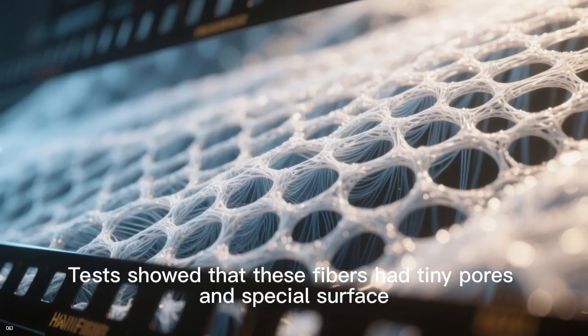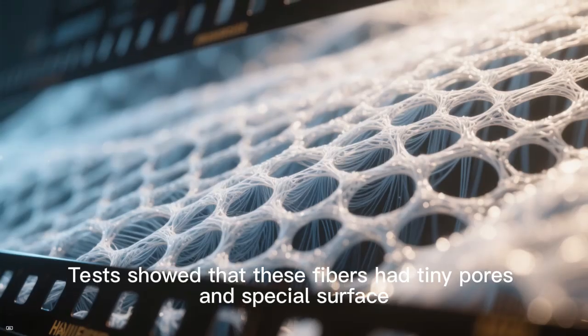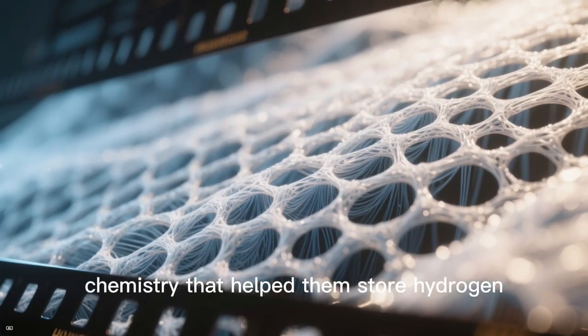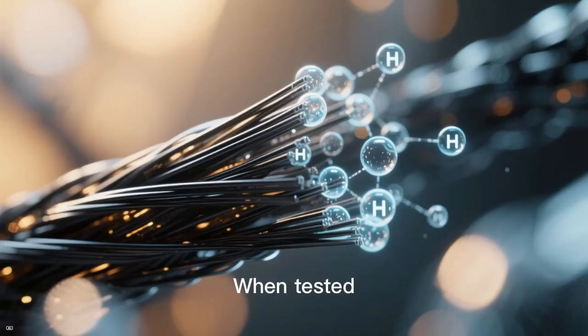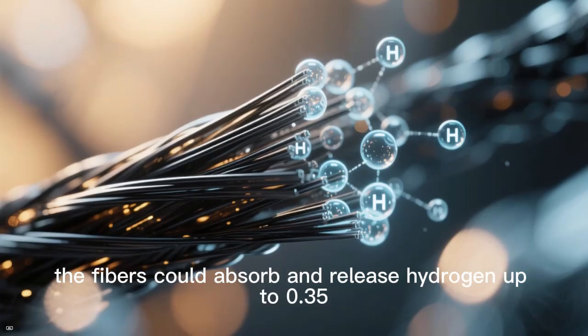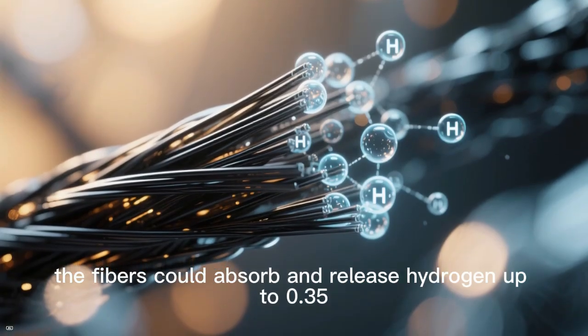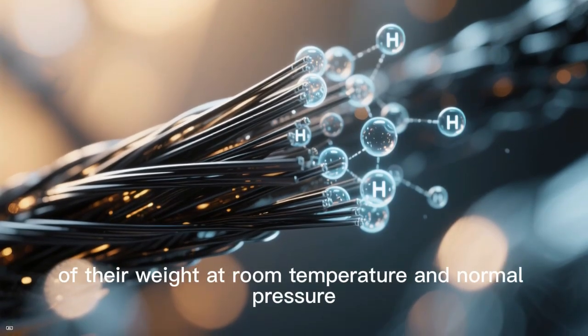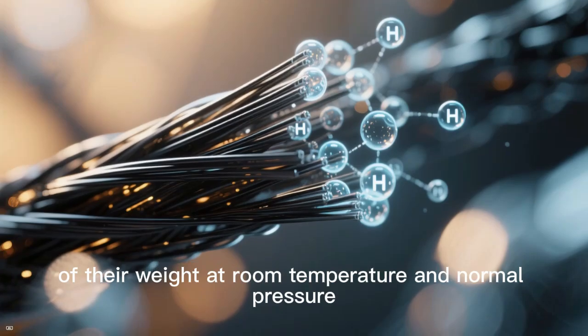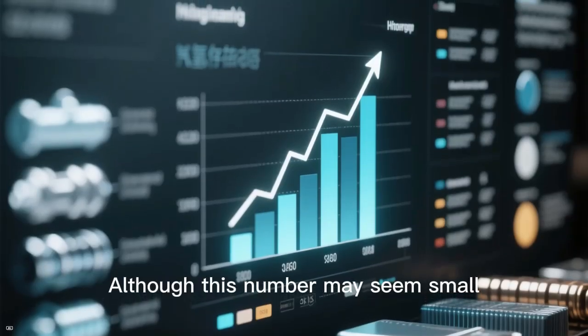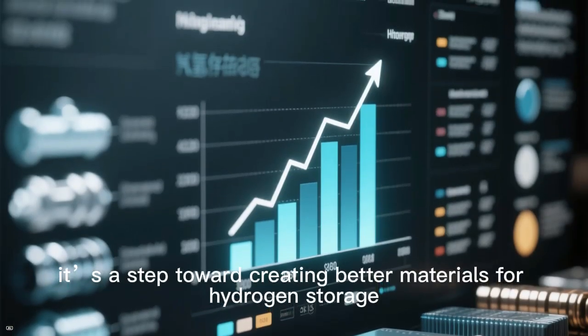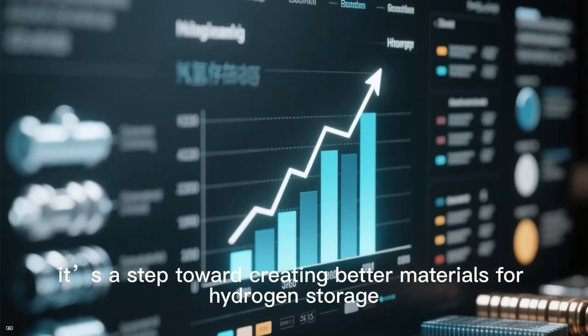Tests showed that these fibers had tiny pores and special surface chemistry that helped them store hydrogen. When tested, the fibers could absorb and release hydrogen up to 0.35% of their weight at room temperature and normal pressure. Although this number may seem small, it's a step toward creating better materials for hydrogen storage.